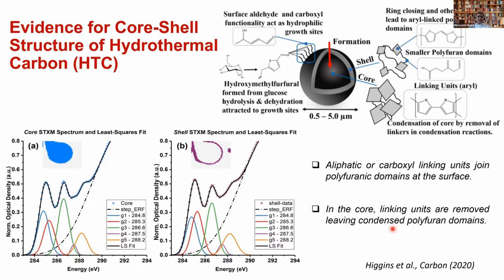Although the carbon, nitrogen, oxygen ratios are very similar, and that is why people had failed to understand the difference between core and shell using things like XPS and other techniques, because the empirical ratios remain the same. The way they bond and the way the carbon moieties are formed is different on core versus shell, and that was a very big deal because hydrothermal carbons can be used as capacitors. It has already been shown that they can be, and so tuning the surface properties is very important.